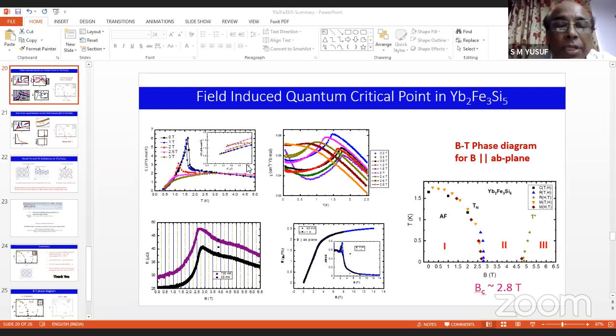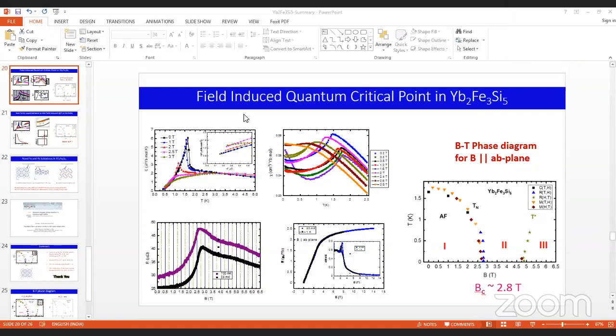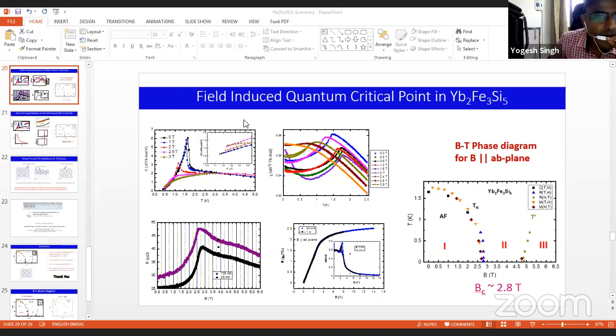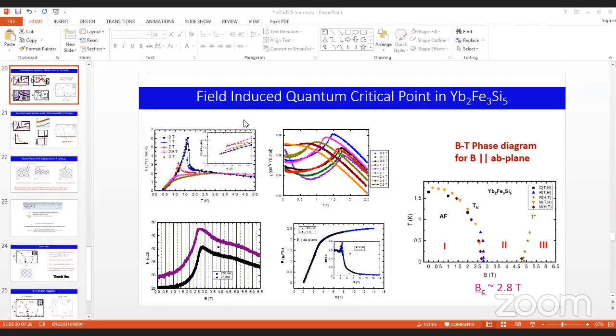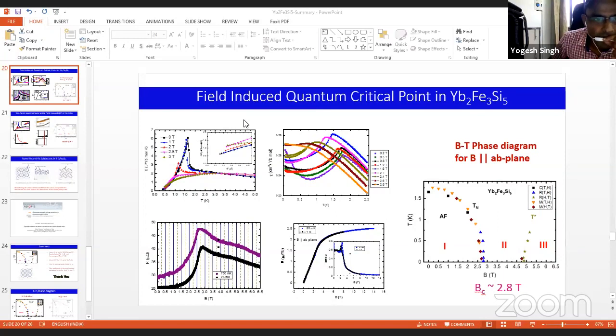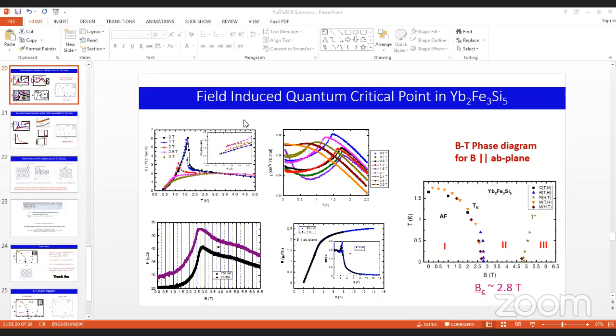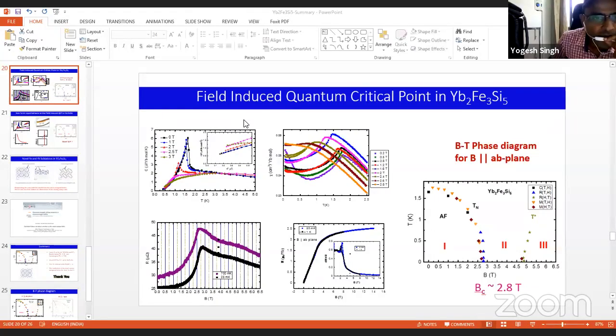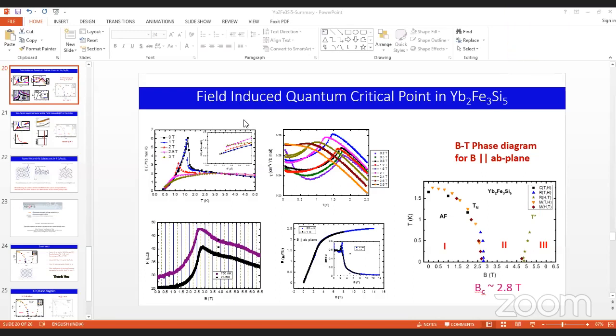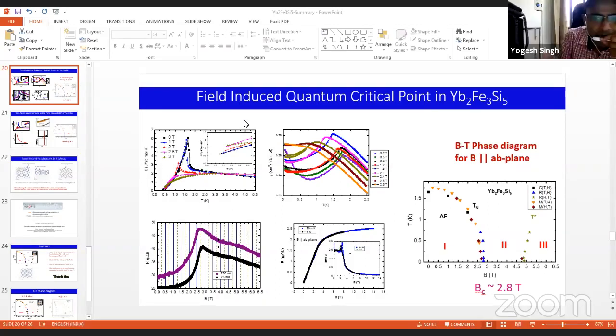Okay. Any other questions from the audience? I have a question. Can I ask? Yeah, please. Please identify yourself. I'm Pratyay Ghosh. So what I'm asking is, your spins seem to be confined to the basal plane, right? And from the anisotropy, it seems to be that way. Is it coming from the crystal field effect or something else? Most likely from the crystal field, because you see that the single-ion anisotropy is already seen at 300 Kelvin, so it can't be some energy scale which is small.